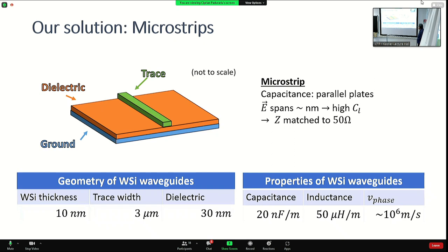And for the kinetic inductance amplifiers, this is barely feasible to get enough capacitance to make this close to 50 ohms. Actually, it typically fails and what you do is you do these Klopfenstein tapers in order to transition adiabatically within a certain bandwidth to much higher impedances. And that actually significantly extends these amplifiers to be chips of a few centimeters with lots and lots of coils and a lot of microwave engineering. There's all interesting fractal capacitance work that was done in various places, also in Chalmers. And these are barely feasible. It's just very hard to accumulate the proper parameters for this. And you get these highly rippled gain curves because of this. And we went for something which, in the end, it's sort of obvious, but it has this elegance to it. The idea of having this kinetic inductance trace but a very narrow dielectric gap to a ground gives you a huge capacitance per unit length.